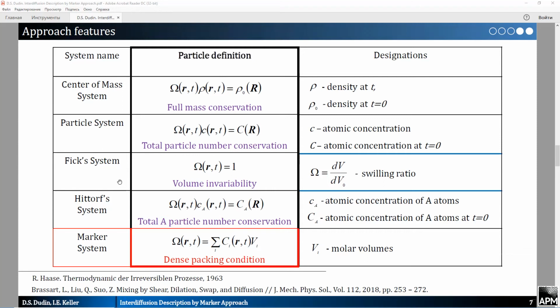In Fick's system, a current macroparticle volume always coincides with the reference particle volume. Next is the Hittorf's system, in which it is assumed, for example, that the total number of A particles is constant over time. And finally, we have the marker system, in which the current macroparticle volume is represented by a sum of individual atom volumes.